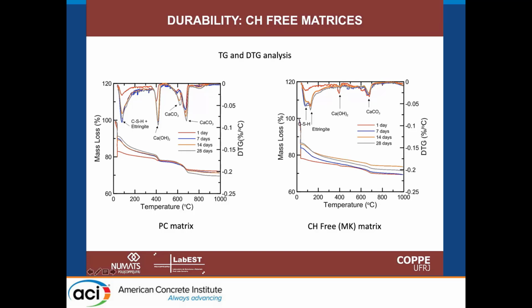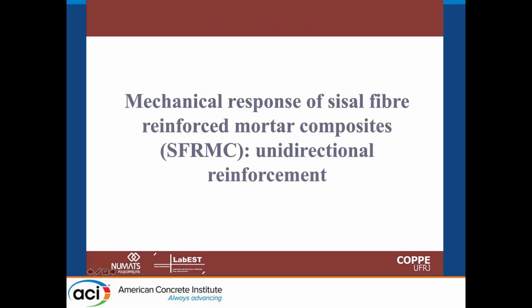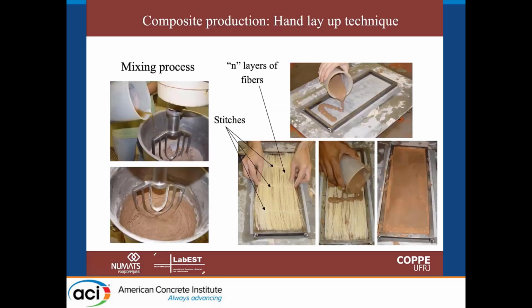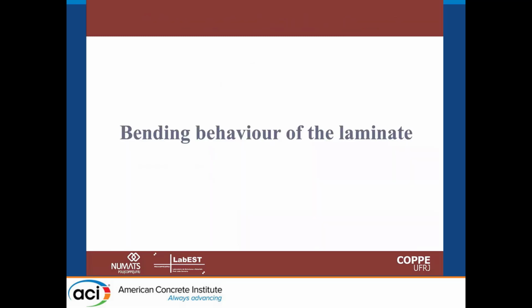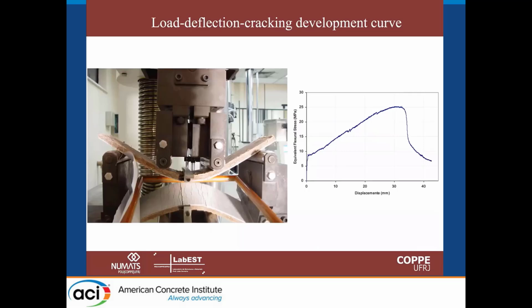In the design, the important thing is that the CH-free matrix does not have calcium hydroxide in the composition, as it can mineralize the fibers. Just to show you the potential of these materials, I'm presenting here long aligned fibers, so it's built in layers. When we test them in bending, we can see here a bendable concrete made with long aligned fibers. In this case, we have 6 layers. We can achieve 25 MPa of equivalent bending strength.